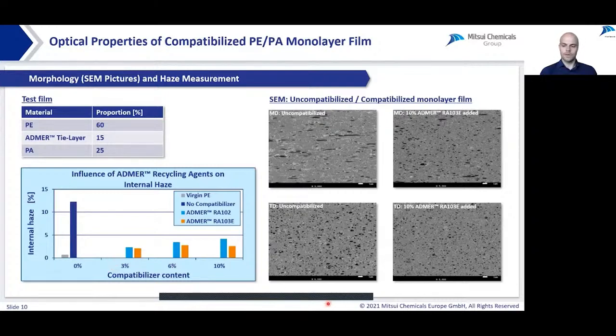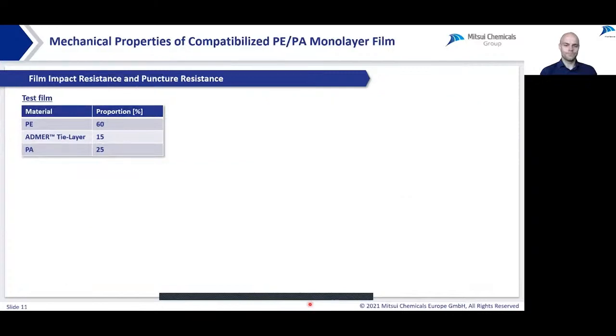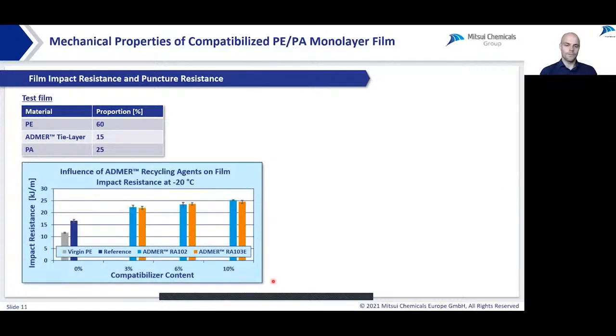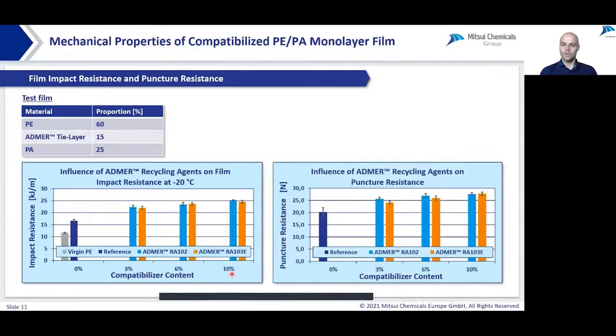But this is not the only advantage of a finer morphology. The mechanical properties improve as well. Compared to the uncompatibilized reference, our ADMER recycling agents are modifying the test material to a higher film impact resistance. The same observations can be made for the puncture resistance. For the sample, the puncture resistance can be increased about 40% compared to the reference material without compatibilizer.